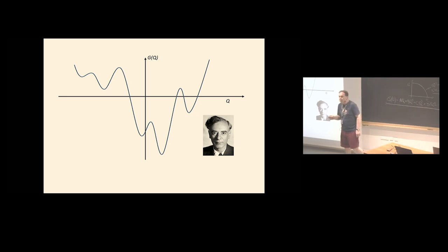Now what we know is that symmetry is demanded such that plus Q and minus Q are equivalent and therefore have the same free energy. Well, that means that you cannot have a linear term to your free energy statement because a linear term would have the free energy component as a function of Q looking like this, and clearly then the free energy of plus Q and of minus Q are not going to be the same. Okay, so any of those odd exponents have to go straight in the bin, in general. Okay, that's the first, I don't know how many steps of genius there are.